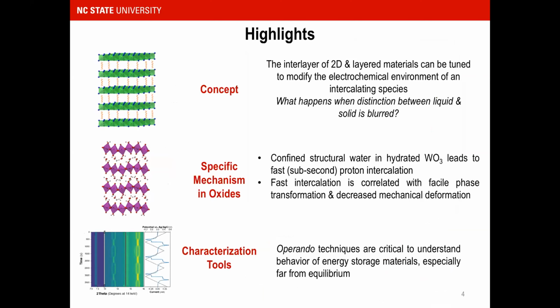And from a philosophical standpoint, what happens when that distinction between what is actually a liquid and what is solid is blurred under this extreme confinement? Then I'm going to talk about a very specific mechanism we've discovered in tungsten oxides, where we find that the presence of structural water leads to extremely fast proton intercalation, and how we used operando characterization tools to find that it's really related to the mechanical deformation that occurs in these materials and how structural water minimizes that.